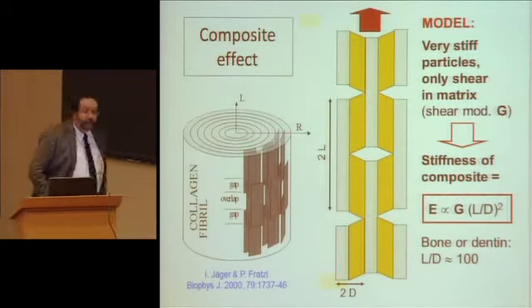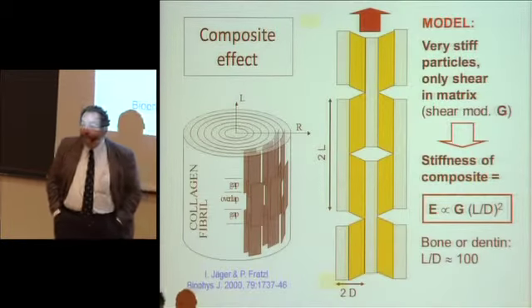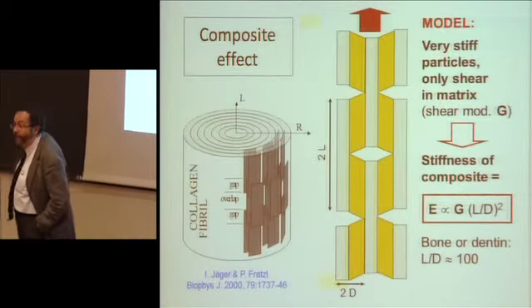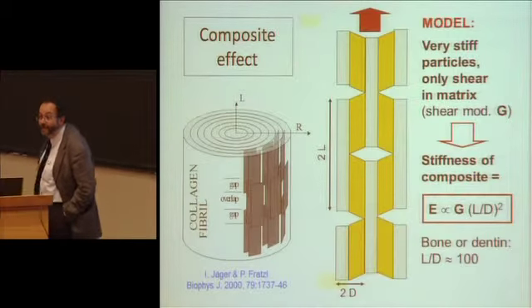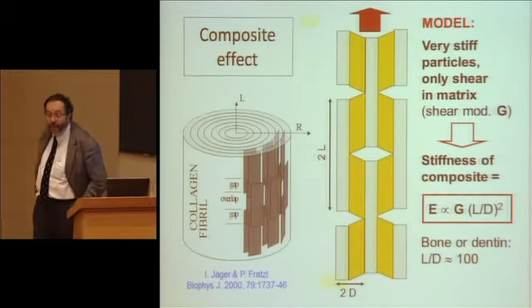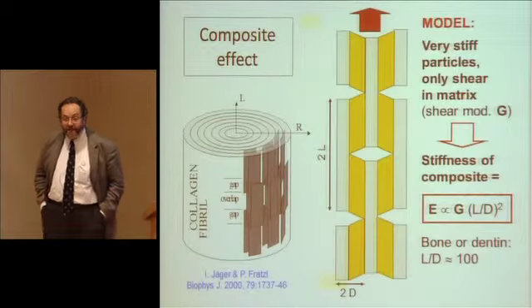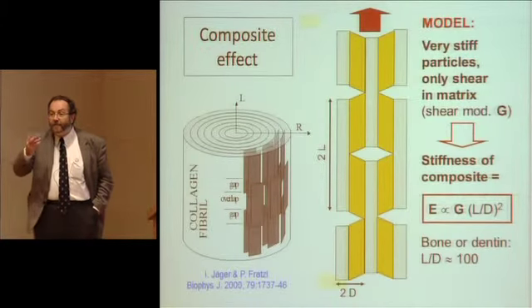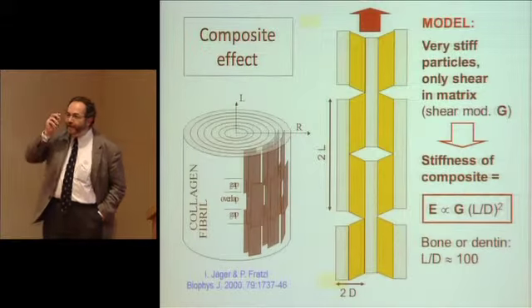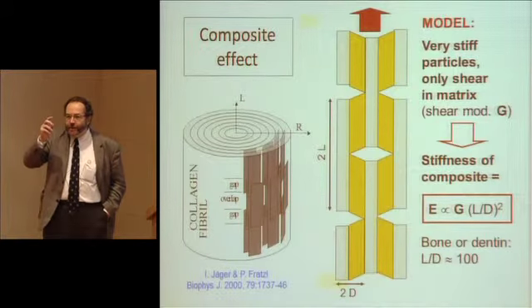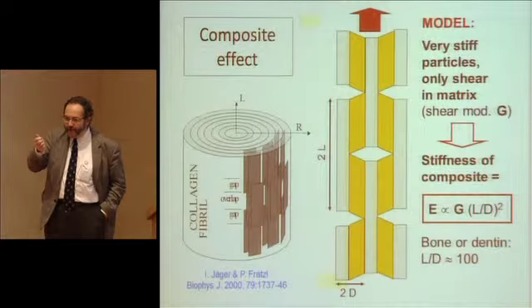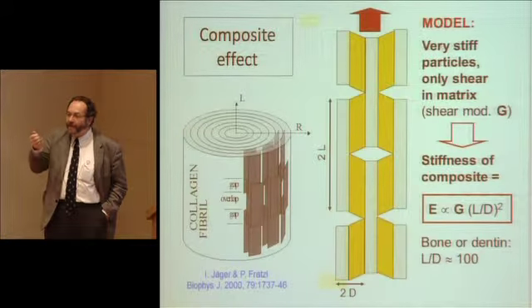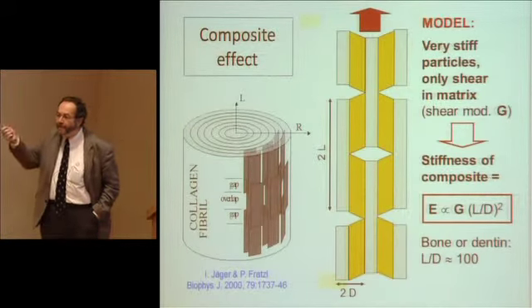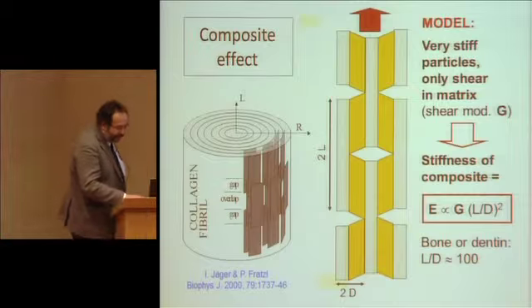If you take bone or dentin, which is what constitutes your teeth, you can have a factor of 10 to the power of 4 between the shearing modulus of the polymer and the Young's modulus of the composite. What you can draw from that as an engineer is you can be in a situation where if you have a very powerful aspect factor, you can have a much higher modulus than the modulus of the weakest part.